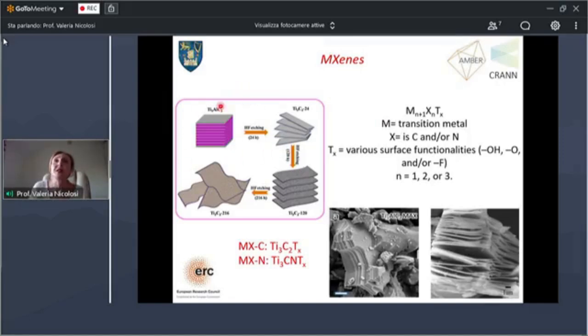The beauty of these materials is that, well, they're not van der Waals crystals like the ones I showed you before, but these are layered crystals where you have strong covalent bonds in plane and also strong covalent bonds out of plane. So what we do normally is HF etching to break the interlayer bonds, and we go from a max phase that is like that, layered but basically bound together only by covalent bonds, and we transform it into this sort of accordion type of structure where it's a swollen type of structure.